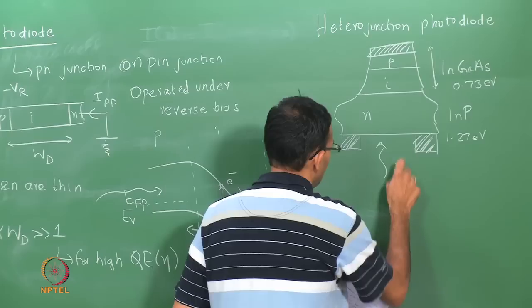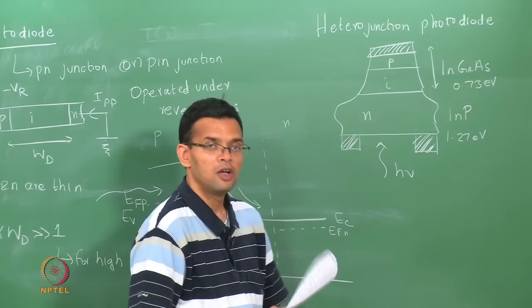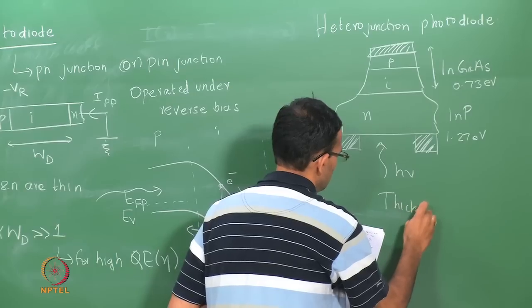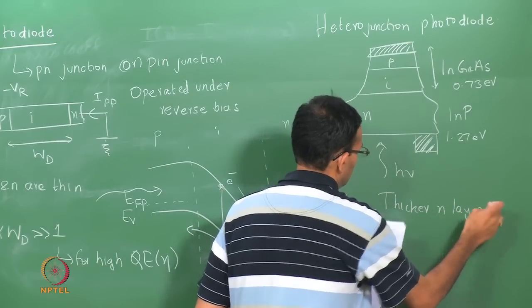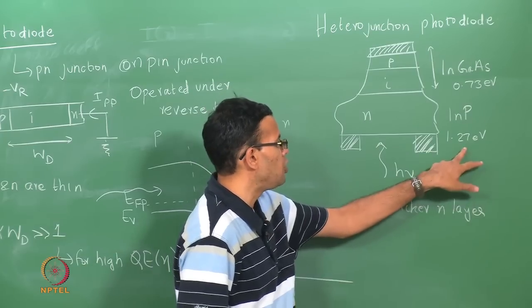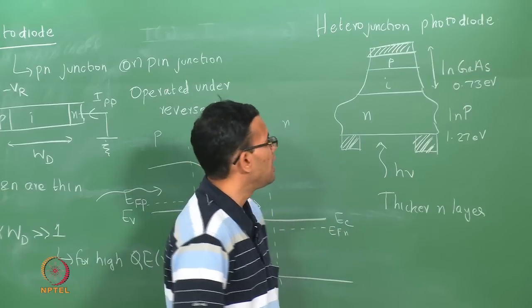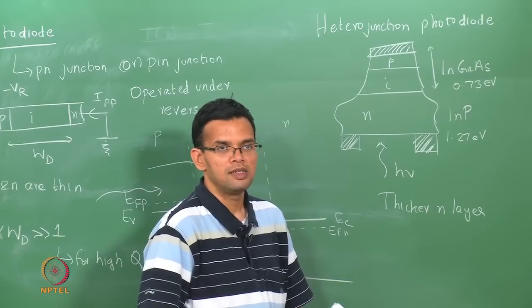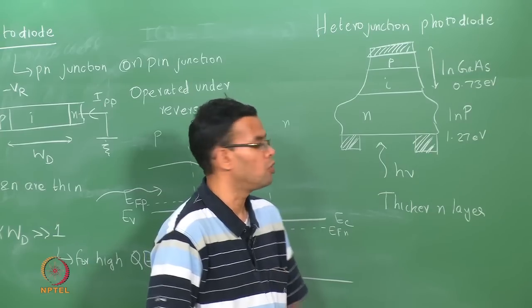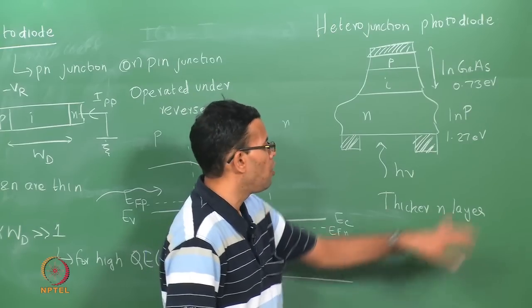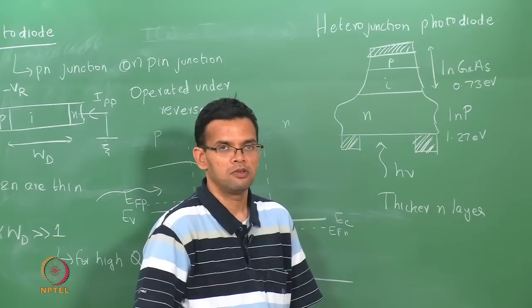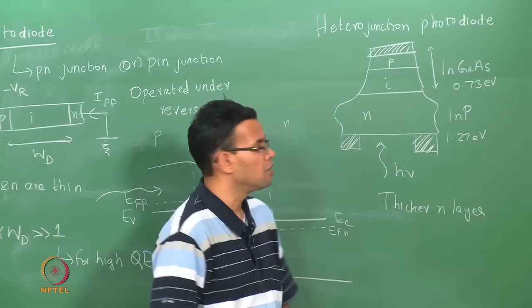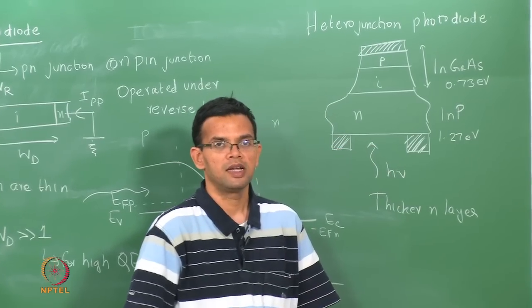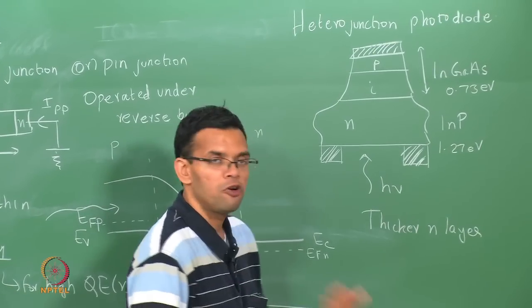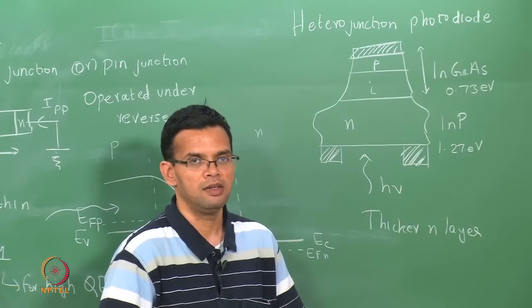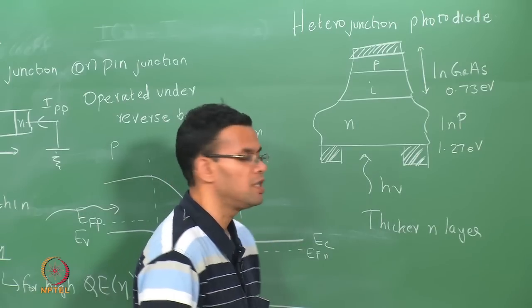So, in this case, light shines from below, so that you can have a thicker N layer, so that all the wavelength whose energy is below 1.27 will get absorbed. Another advantage of the heterojunction photodiode is that you can cut off certain portions of the wavelength that you don't want. For example, if you do not want to look at wavelength above 1.27, by having a thick N region, those wavelengths or those energies can be absorbed, so that only wavelength of a certain range can be detected by the photodetector. So, the heterojunction photodiode works on the same principle as a regular PN or a PIN, but offers added functionality because of the difference in the band gaps.